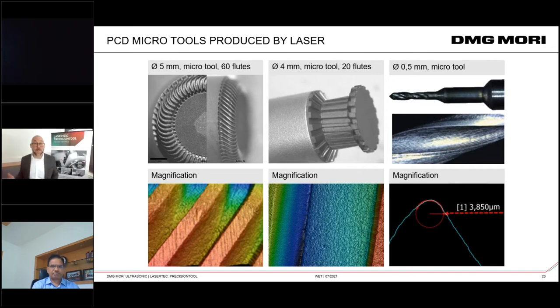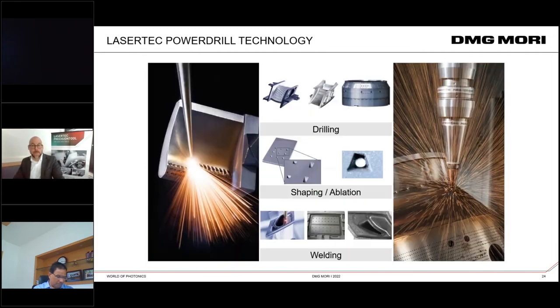On the right-hand side, we do see a 0.5 millimeter micro tool made from diamond. How are you machining a diamond? With laser machining from DMG MORI, this is possible. Very sharp cutting edge of close to 4 micrometer. So this tool is really aggressive and doing a great job for the cutting process.